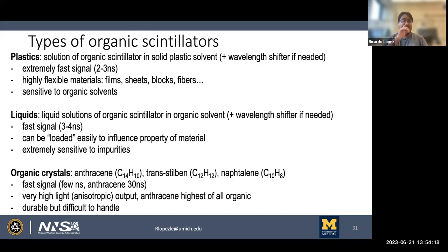For example, in cases where you need a high amount of efficiency, well, due to the inherent low density nature of organic scintillators, you need something with a large volume to make up for that. As such, you would use plastics, since these could be made in very large quantities. So you would overcome the efficiency issue by just having a very large plastic scintillator be used.